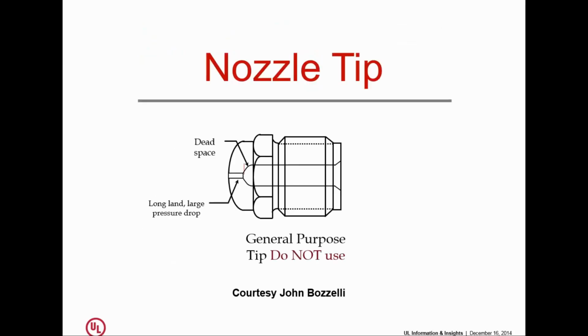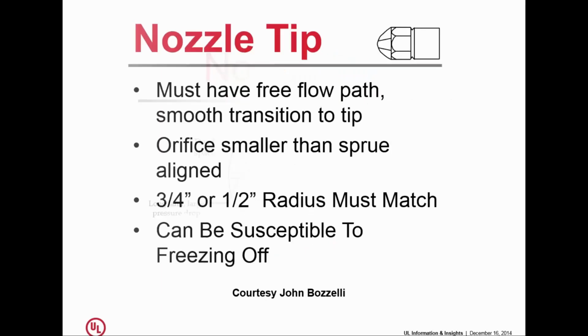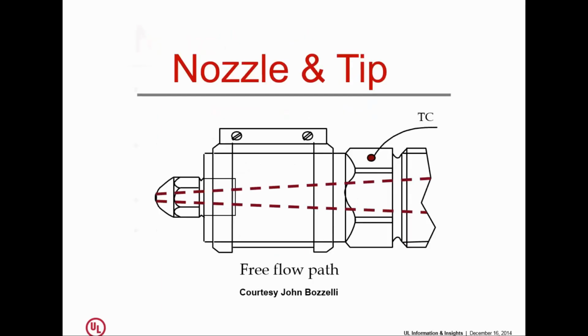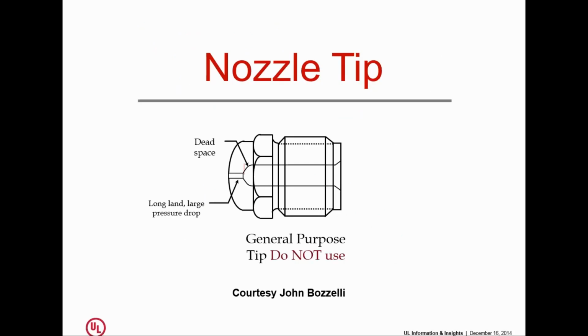One thing you do not want to do is use this kind of nozzle tip. This is what's called a general purpose tip. This has a straight flow path. This area here constitutes a dead spot, and this represents a very long land, which is a big pressure drop. It's hard enough to get the plastic to go in where we want it to go without making life more difficult by putting nozzle tips on the end of the machine that make it even worse. So if you have these in your plant, do one of two things. Drill them out so that they look like what I showed you before, or throw them away and don't buy any more.